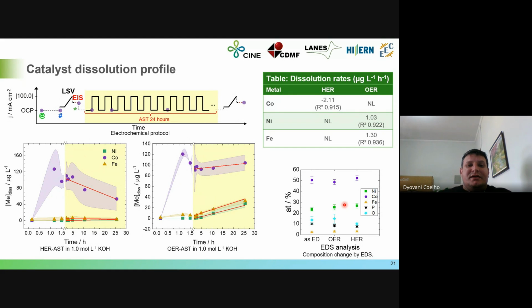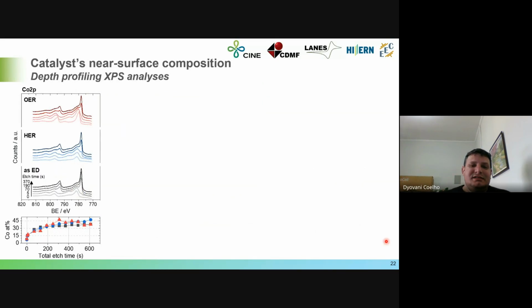But for the bulk concentration of the catalyst, this change is not significant. This was analyzed just by EDS analysis, but EDS is a bulk concentration technique, not a surface-sensitive technique. So let's go to a surface technique to see what is happening in the near surface, underneath the surface. Let's start with the depth profile XPS analysis of the cobalt,